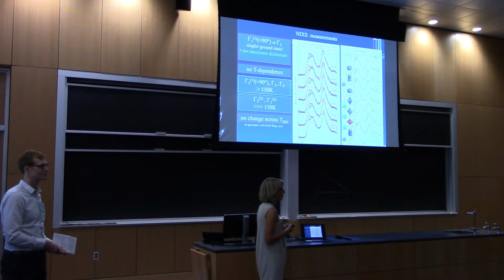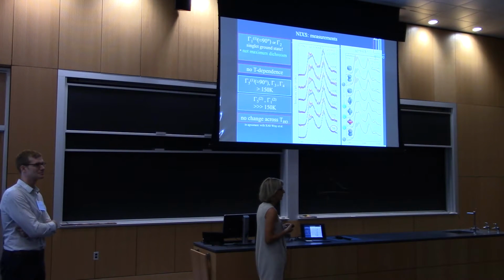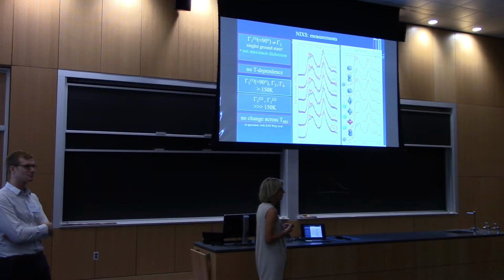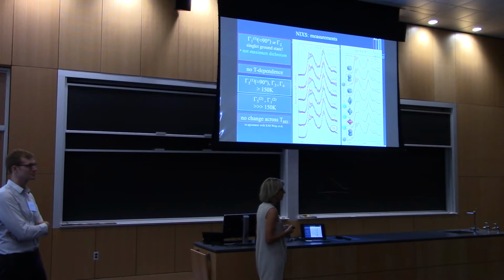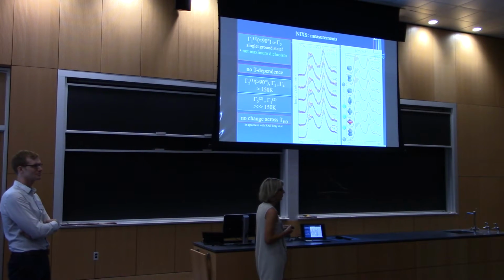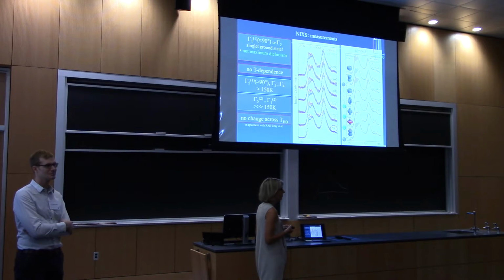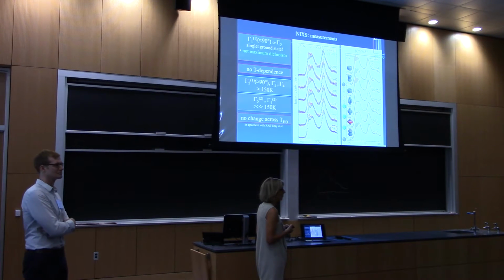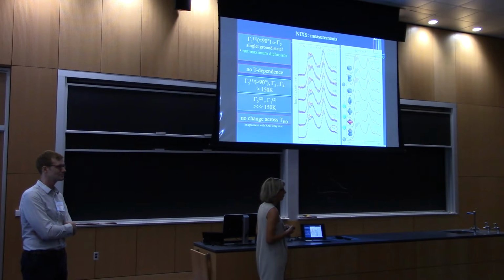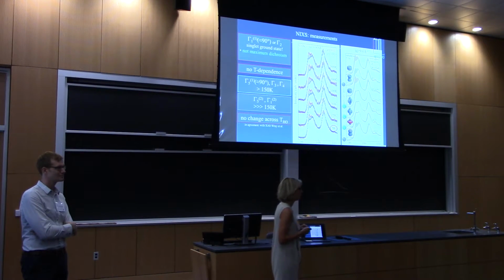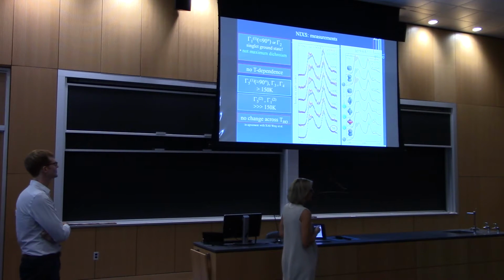The gap opens up because there is a spontaneous symmetry breaking, a second order phase transition. What breaks the symmetry, I think we identified in our study: it's the mixing of gamma 1 and gamma 2, which didn't happen above the transition and happens below it, and that opens up the possibility. That's the driving force. Basically, gamma 2 wants to be lower than gamma 1, and it's forbidden. So this is entirely consistent with that.